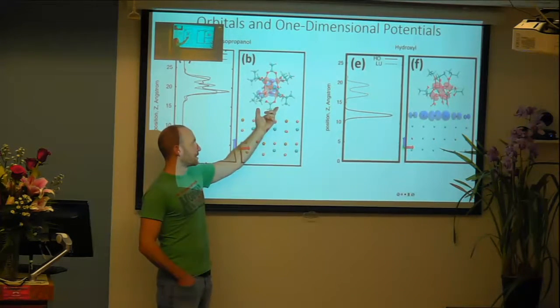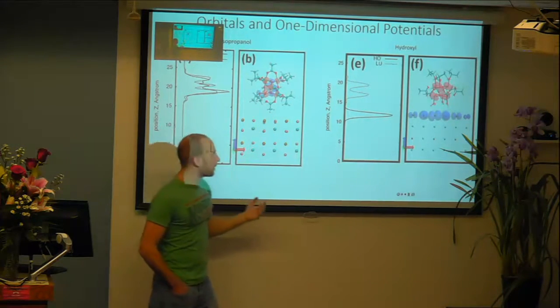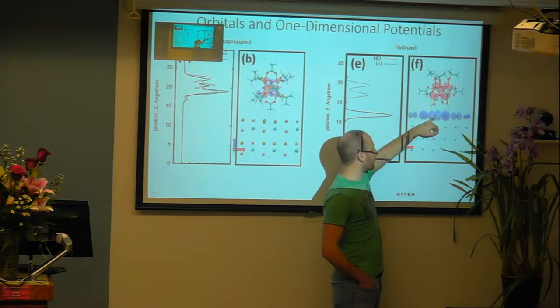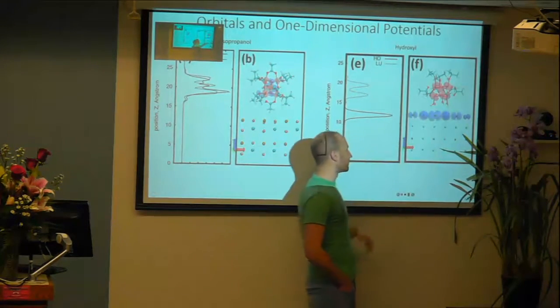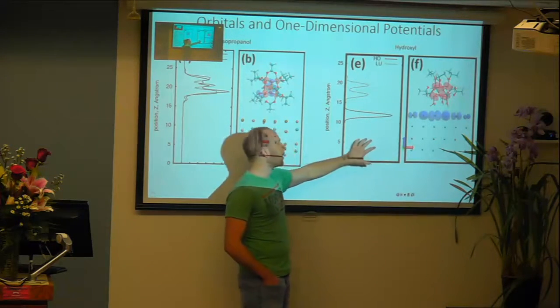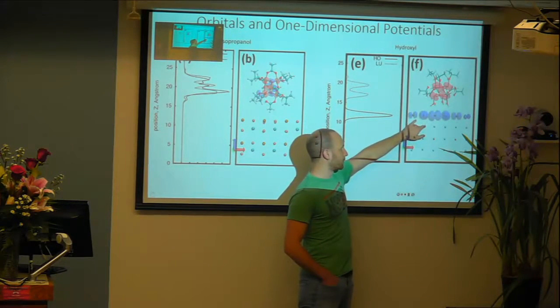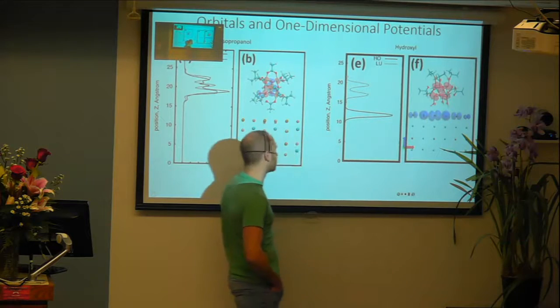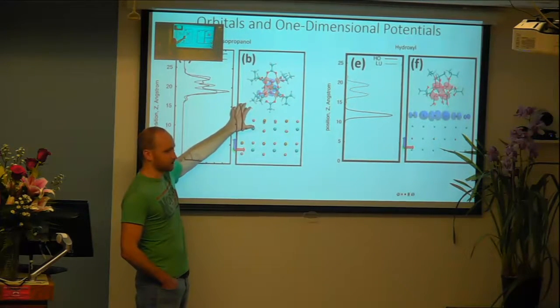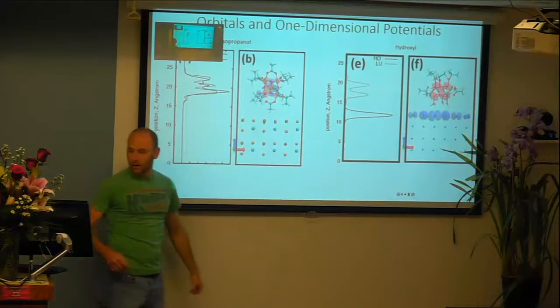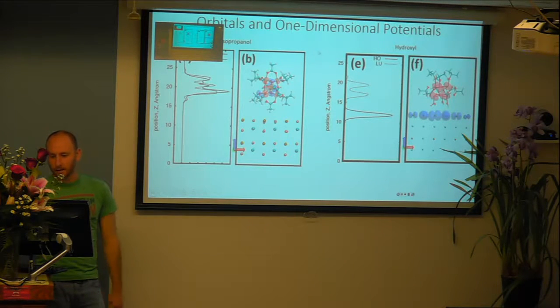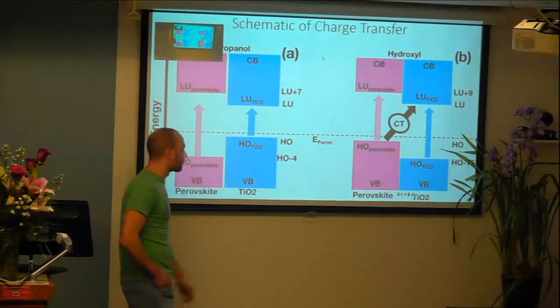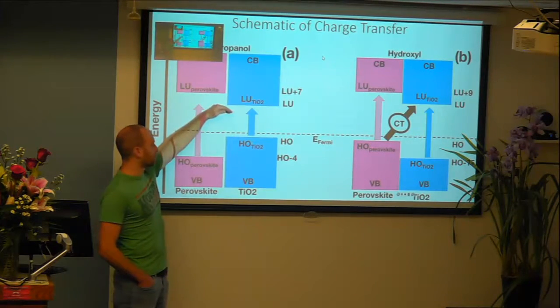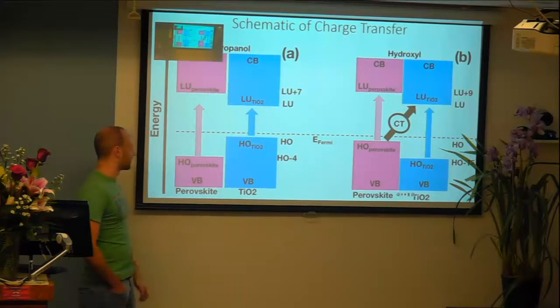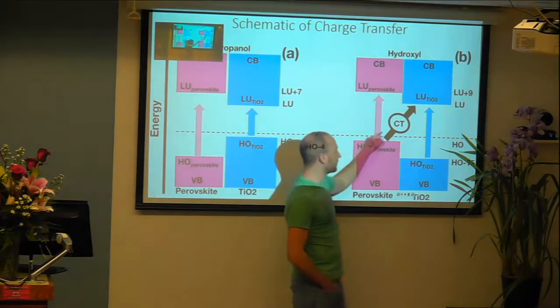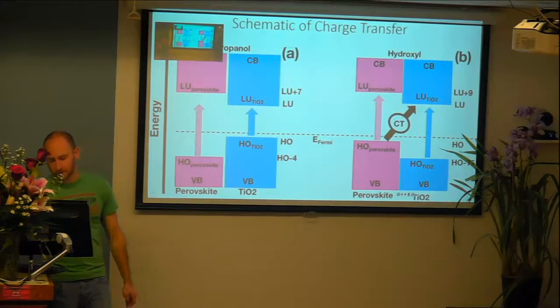You can see that those are both localized on the titanium dioxide in the isopropanol case, whereas in the hydroxyl case, you have the HOMO in the perovskite and the LUMO in the titanium dioxide. This would be preferable because as you create an excitation, if the electron jumps into the next orbital, it will move over to the titanium dioxide, whereas in the isopropanol case, the charge doesn't end up going anywhere, so you don't get the desired property we're looking for. So this suggests that the hydroxyl is probably better in that regard as well. This is a schematic of what I was just talking about, where the lowest energy jump would be from titanium dioxide to itself, whereas in this case, you would transfer the charge over to the titanium dioxide from the perovskite.